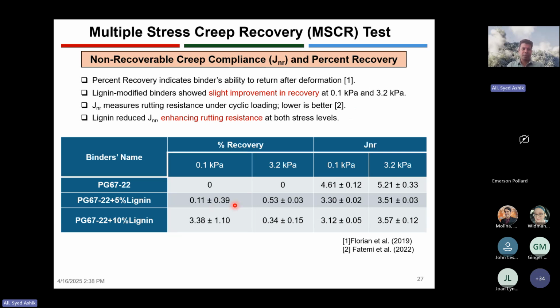Okay, we can expect some recovery, a higher amount of recovery than the neat binder, but as lignin is not a polymer product, it did not impact the percent recovery that much. JNR on the other hand represents the rutting resistance under cyclic loading. A JNR value that is lower is better, right? So we have found that with the addition of 5% and 10% lignin, the JNR value goes down significantly, and it also indicates that the rutting resistance will improve with the addition of lignin.